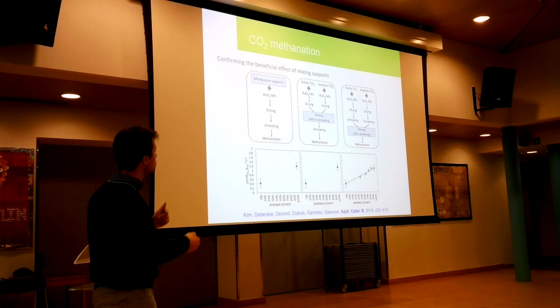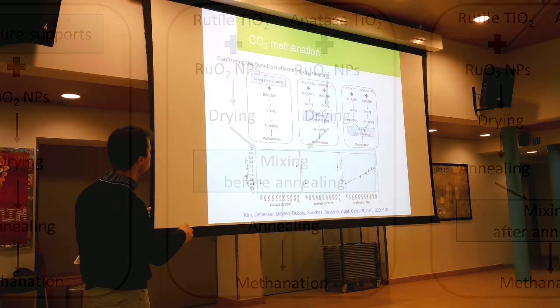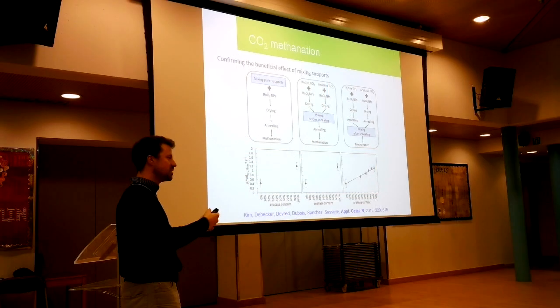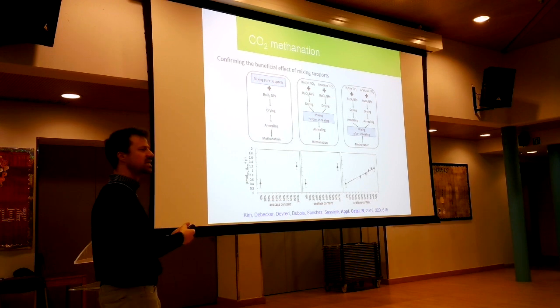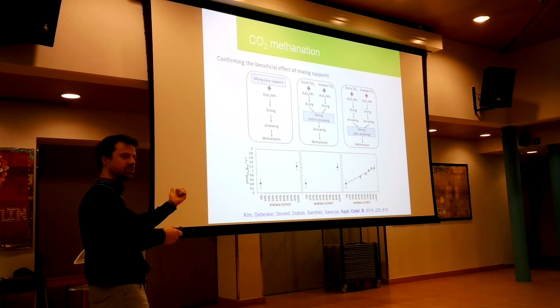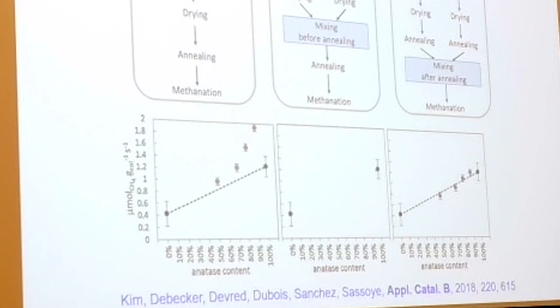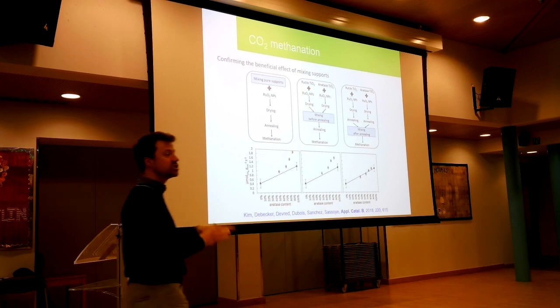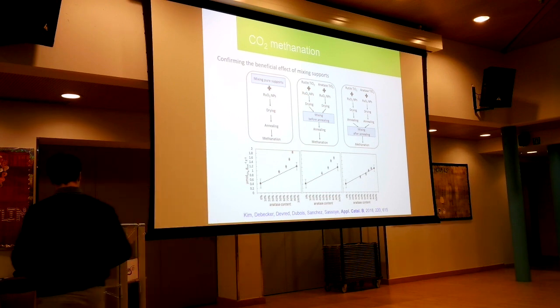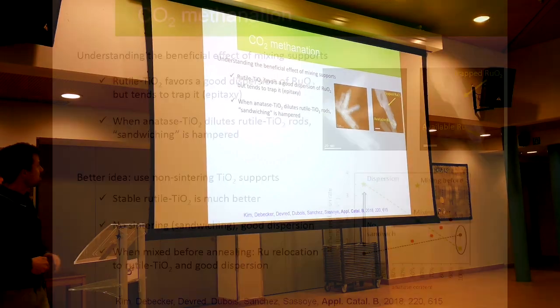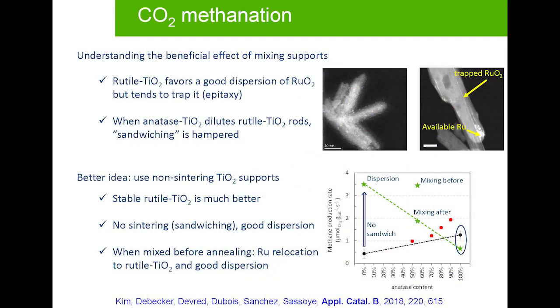Now, if instead of doing that, you take the two supports, you put the ruthenium, you dry, and then you mix before annealing, right? Then it should behave a bit like the P25 that I just showed you before. And this is indeed what we observe, either when you do the mixing at the very beginning or just before annealing, you have, for certain compositions, a beneficial effect of the mixing because you avoid this sandwiching, this sintering, and this trapping of the ruthenium. Time is passing very fast, so I will accelerate on this one.